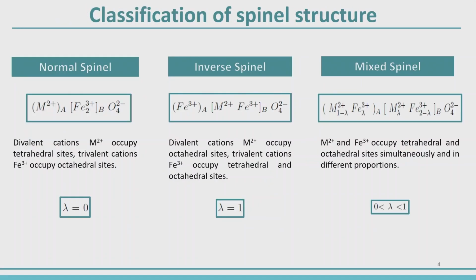This is known, so I'm going to say it very quickly. When lambda is equal to 0, we have normal spinel, in which the divalent cations occupy the tetrahedral sites, and the trivalent iron cations occupy the octahedral sites. We have the inverse spinels where lambda is equal to 1, we know that. Here the iron occupies both tetrahedral and octahedral sites, and the divalent cations occupy only the octahedral sites. And we have the mixed spinels with lambda between 0 and 1, and this can be the cationic distribution in the tetrahedral and octahedral sites.